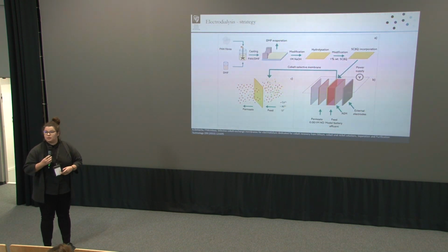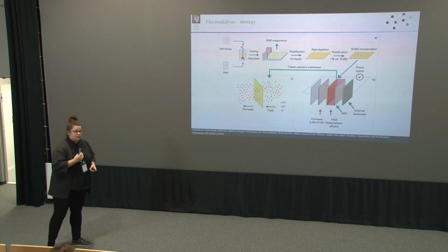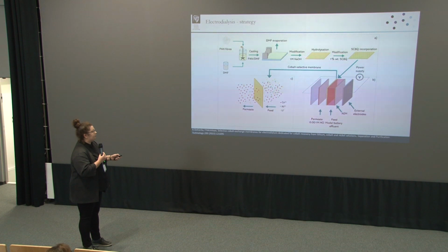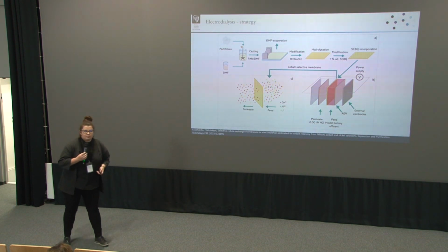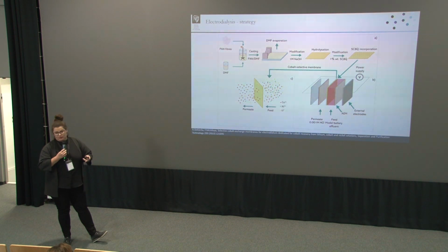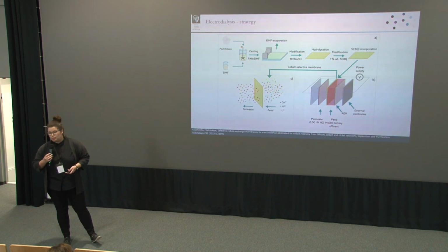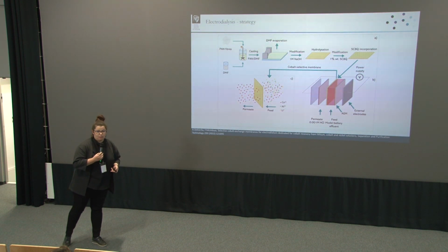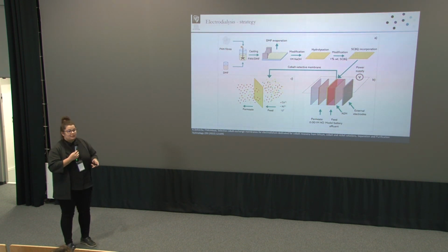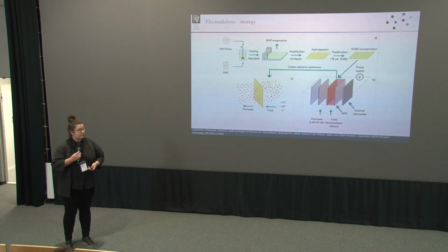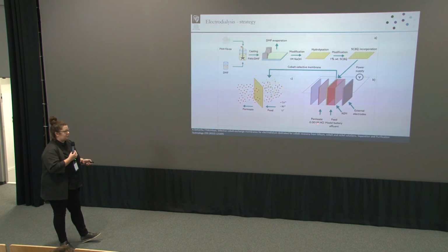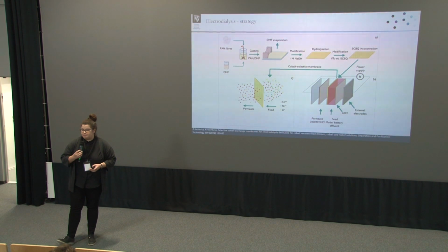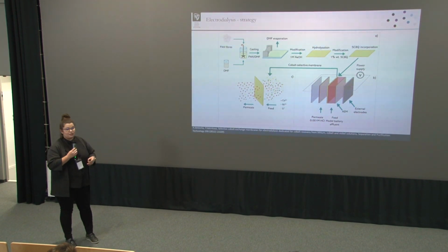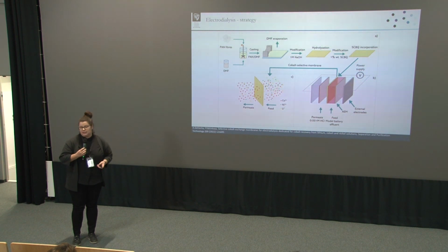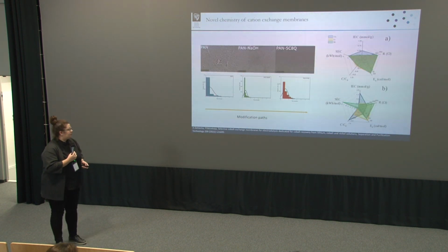To do this, I modified the polyacrylonitrile by a hydrolyzation step to create carboxylic groups. Then I substituted these carboxylic groups with a chelating agent dedicated to cobalt recovery, and applied it inside the ED process. In one compartment I have the feed, in the second compartment I have a low-concentration acid permeate, and I try to push and transport only the selected cation.